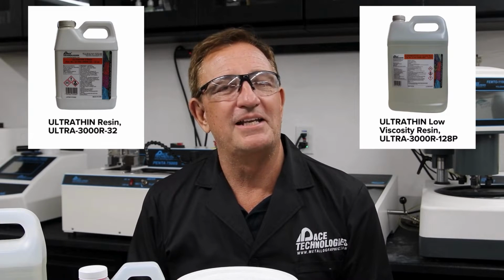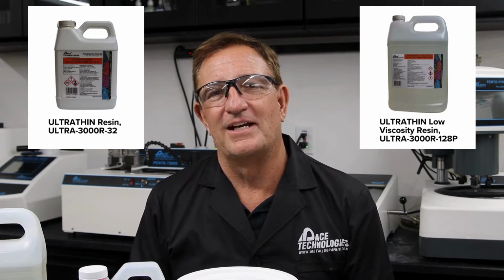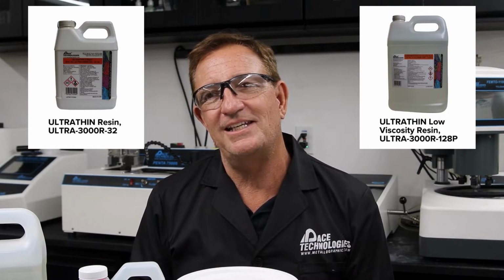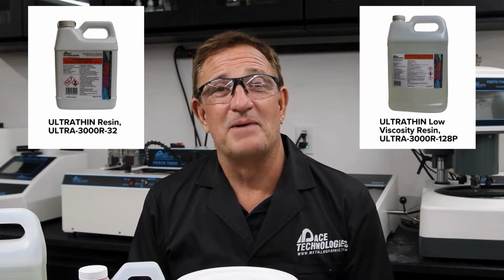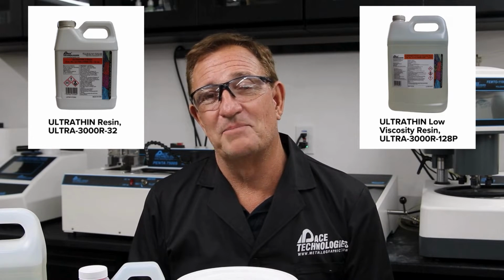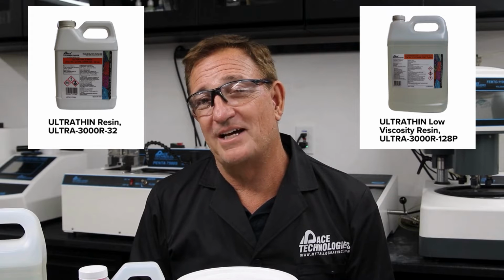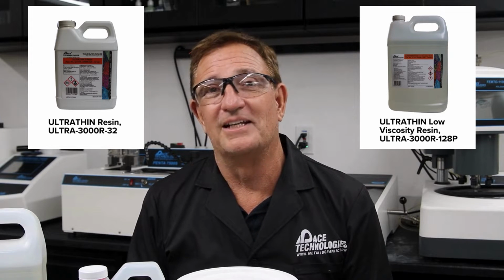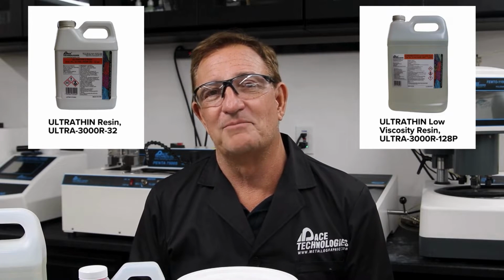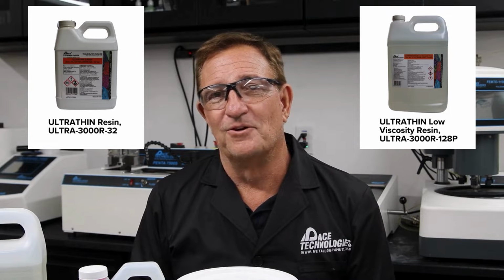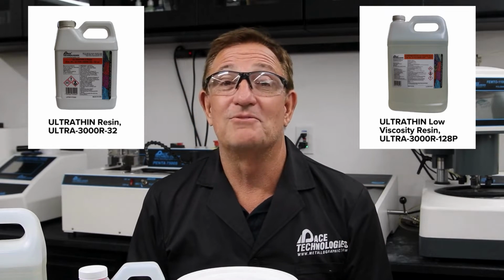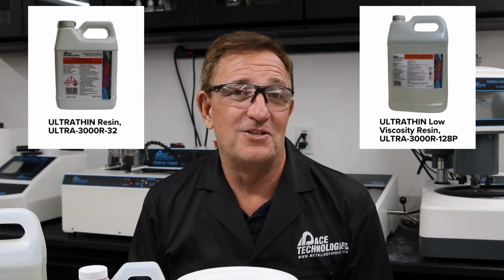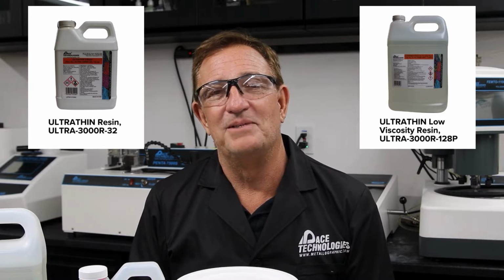Now, epoxies are great, and they come in a number of varieties as well. We offer a low viscosity, a standard curing epoxy, as well as a quick curing epoxy. The quick curing epoxy you've got to be a little bit careful with because it can generate a lot of heat and actually might cause some deformation to your sample. For vacuum impregnation, I would actually recommend the low viscosity because you're starting with a thinner liquid to begin with.